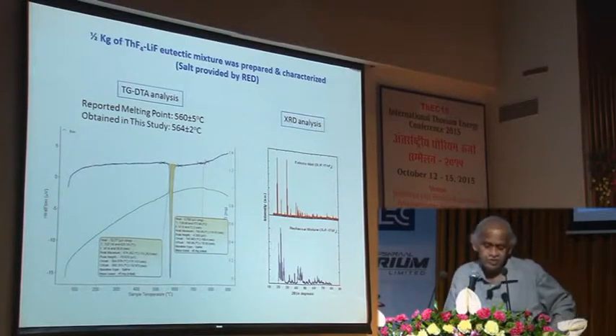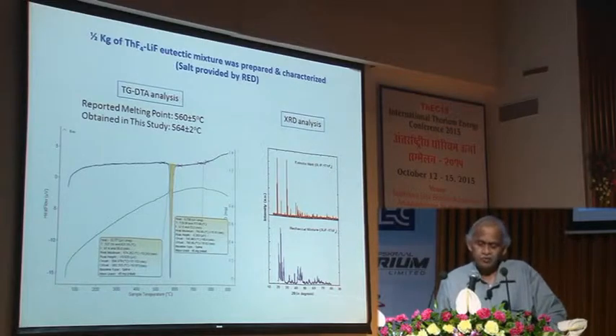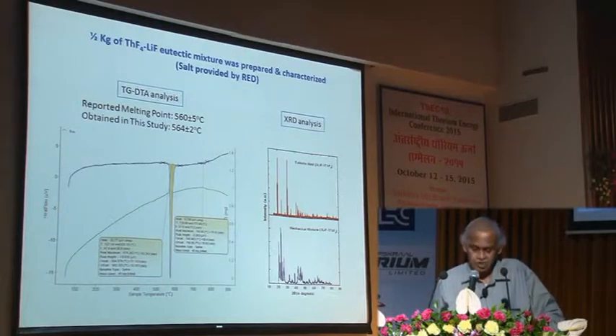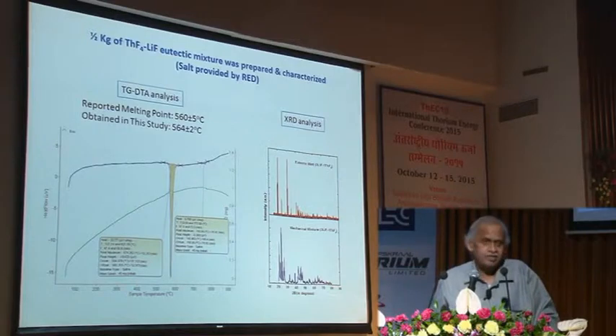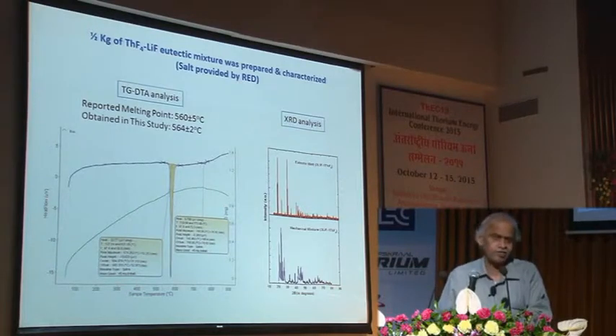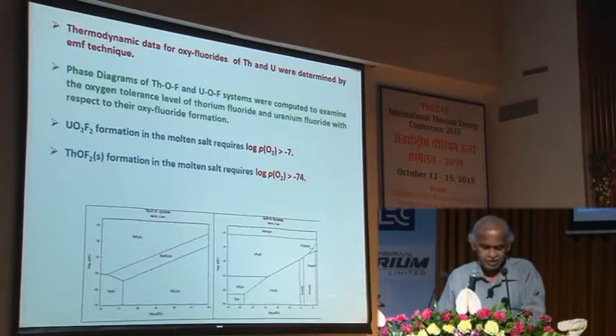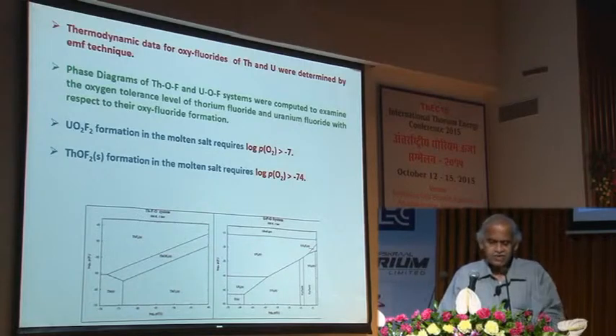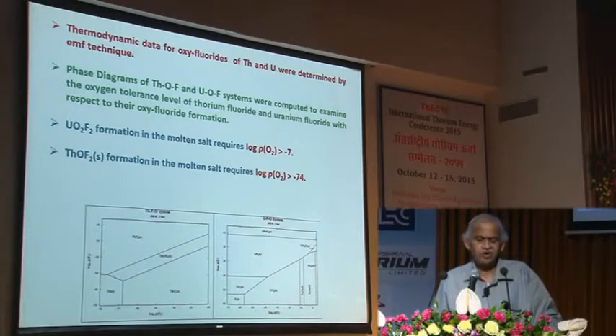and we were able to determine it within 564 plus or minus 2 degrees Celsius, and XRD analysis confirmed that the eutectic has indeed been formed. Probably we will be sharing this information with the reactor engineering division shortly. Just 1 week ago we were able to demonstrate this particular thing. And of course, this is another, the thermodynamic data for oxyfluorides.